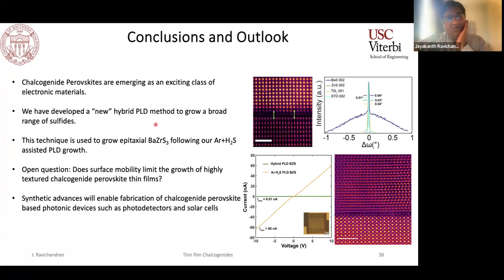So to conclude, I hope that I have shown that chalcogenide perovskites are an interesting class of electronic materials, which pretty much prompted our interest in developing some of the growth techniques I've shown here. We were able to develop this new hybrid PLD technique, which is similar to some of the other approaches that people are thinking about in the oxides. I know Professor Chang-Beom Eom's group at Wisconsin has been working on some of the hybrid type techniques to address some of the stoichiometries on the cationic side. This one is on the anionic side.